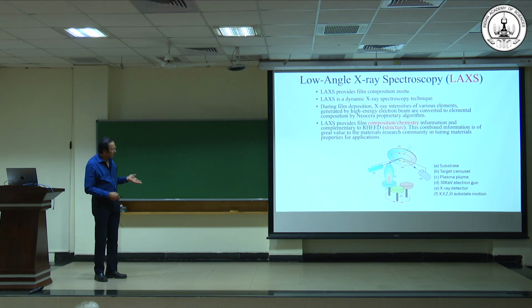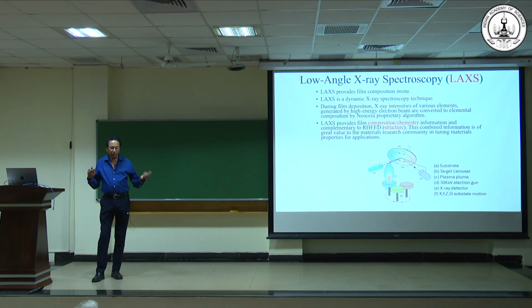As you're depositing the film, what happens is the film is being deposited, the laser comes, strikes a target, material goes up, deposits on your substrate, and then there's an electron beam that measures the film that is being deposited on the substrate. We use this electron beam anyway to measure the crystallographic orientation of the film and so on, and also the film thickness. But the electron beam also generates X-rays when it hits a film. So can we use the characteristic X-rays to measure the composition?